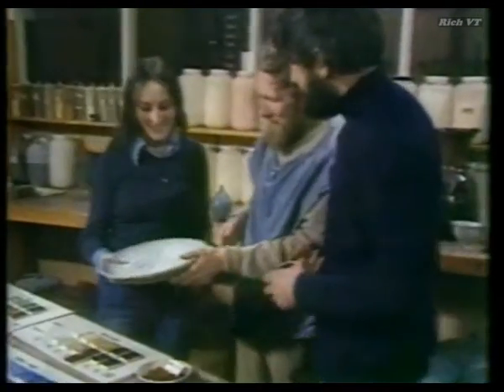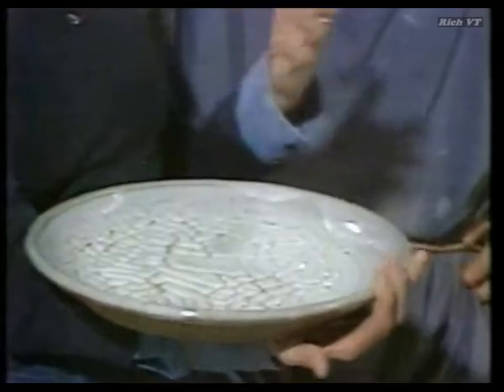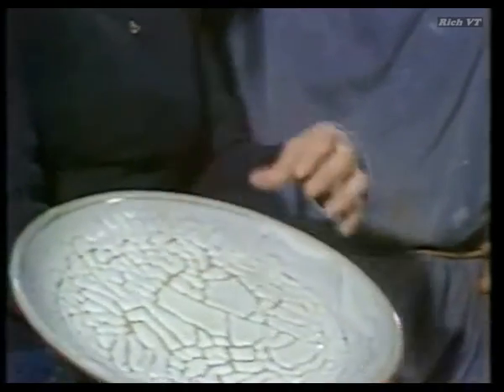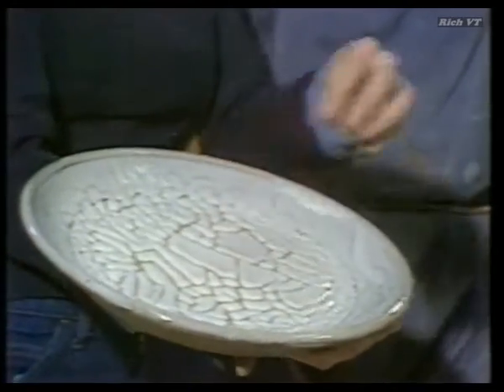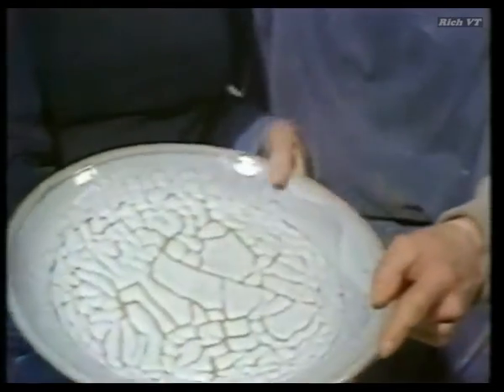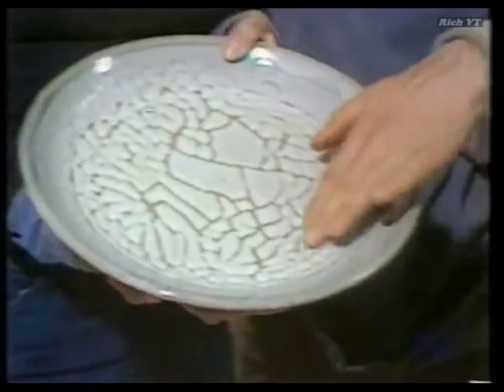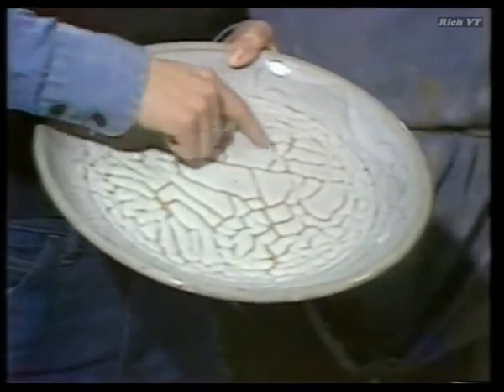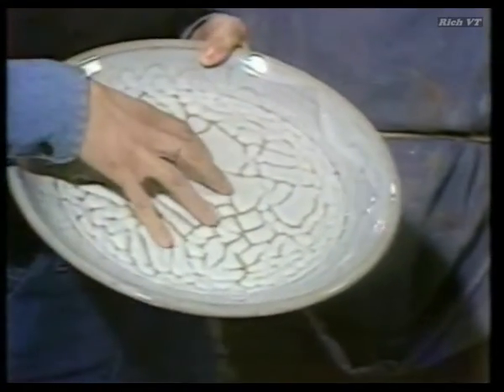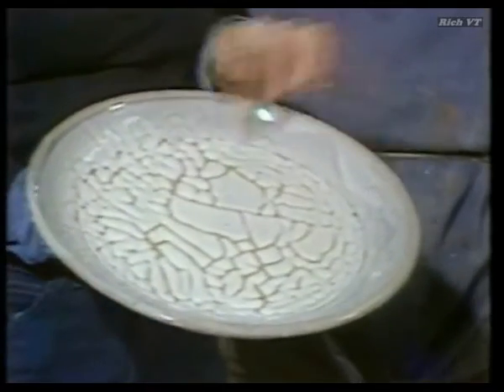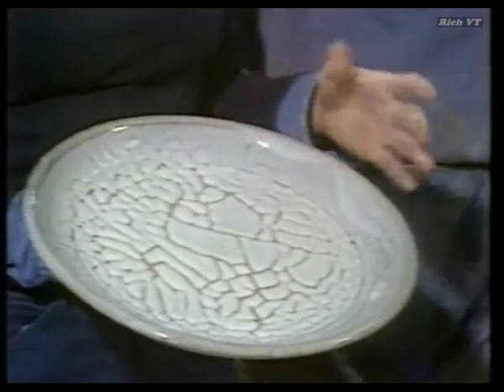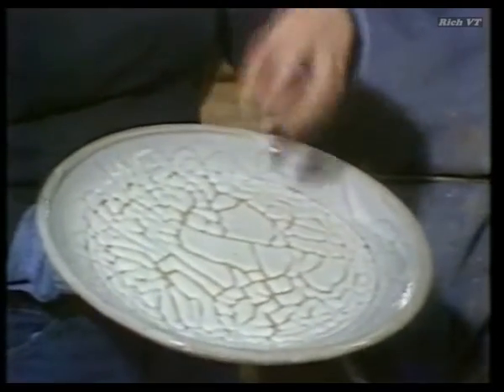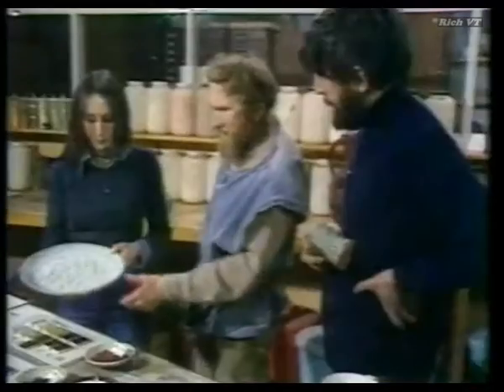I think Wally's got some pots there and some strange things have happened. Lynn, what do you make of that one? Well, this is a defect called crawling, and what's happened is that the glaze has beaded up on itself and left bare patches of clay. I think it may have been caused by the glaze being applied too thickly, or perhaps the biscuit pot before glazing was rather dusty or greasy, and so the glaze couldn't stick properly to the pot. Very spectacular.